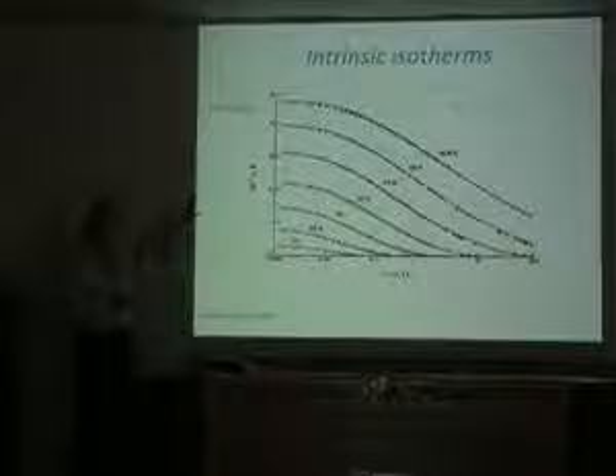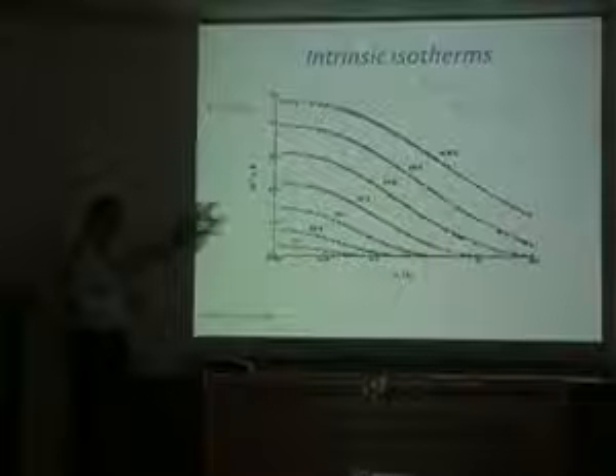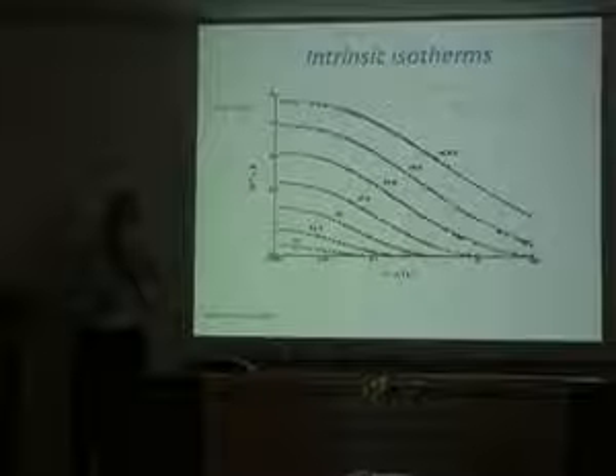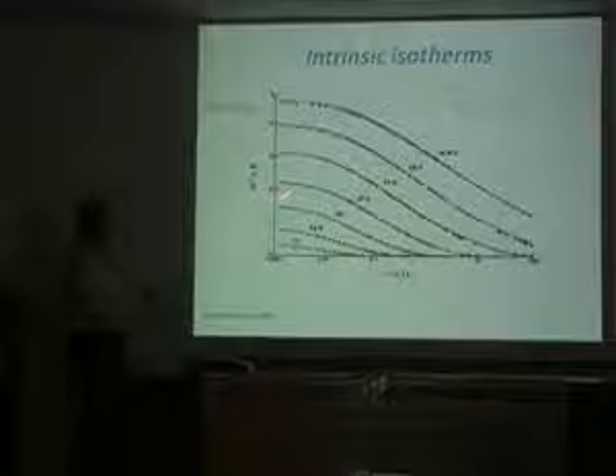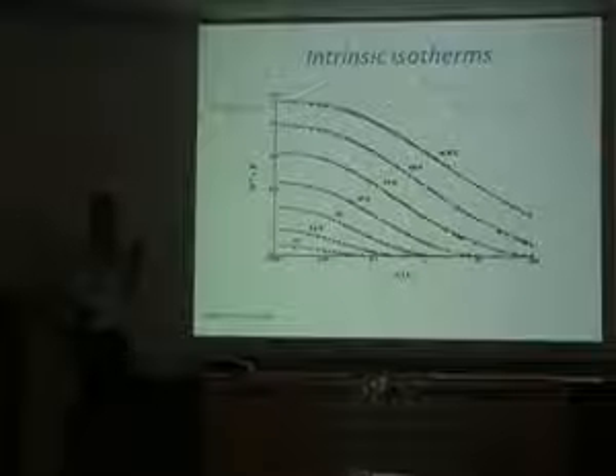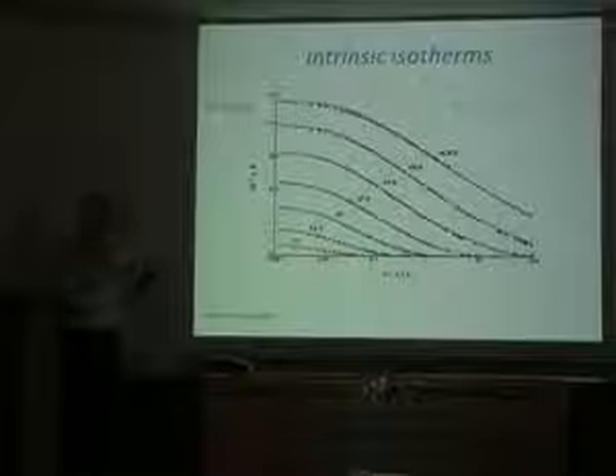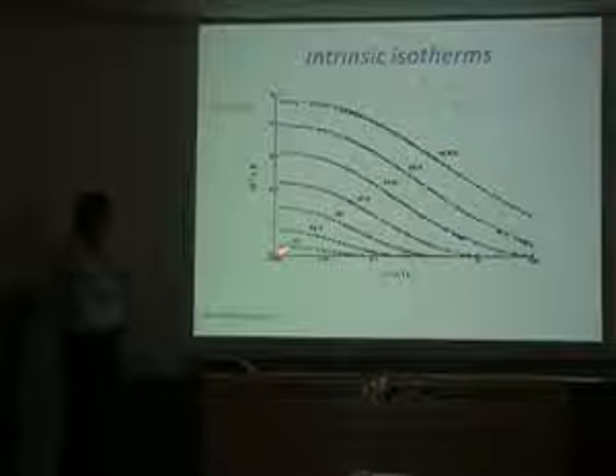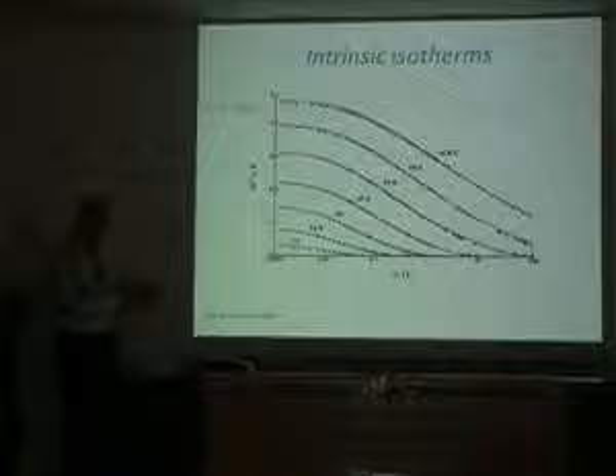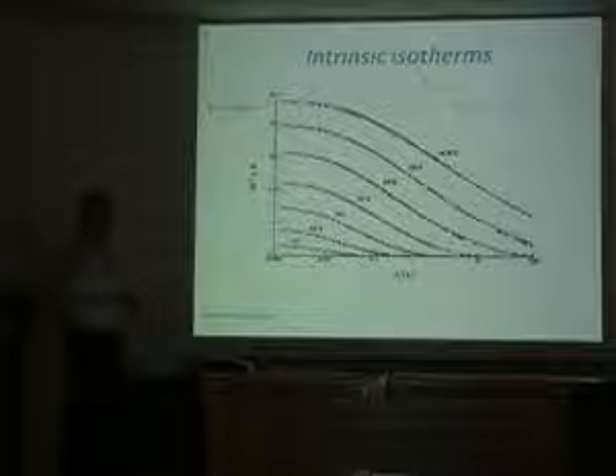And so the intrinsic isotherms look like they're non-exponential. If you just took this information, though, it's insufficient to describe the kinetics of the glass. Okay? Because some people will take this kind of data and fit it to a KWW function. They'll say, wow, not only does the relaxation time vary, but the beta parameter varies. And they say we don't have thermorheological simplicity, for example, or time-temperature superposition. But in fact, this experiment, it turns out, isn't sufficient to say that. All it really tells us is that there's a huge temperature dependence, and it also tells us that there is non-exponential relaxation. Okay?